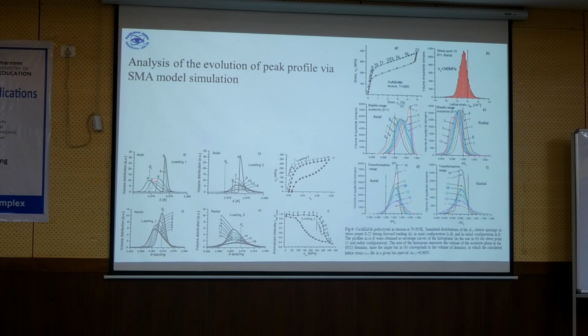So from the experiment, in the beginning, from 0 up to the yield point, there is a main shift. Naturally, this is due to the elastic deformation. As the stress increases, the peak shifts. But then when the transformation starts, suddenly the peak profile analysis gave us very sharp peaks, which even though you increase the stress, don't move more right. So what does it mean? This means that the lattice plane, even if you are stressing the material from 200 to 400, doesn't increase. Macroscopically the stress is increasing, but the lattice plane doesn't.